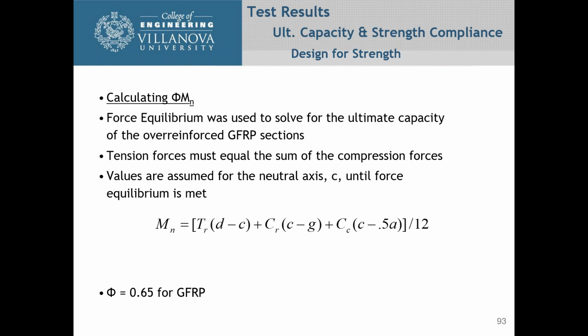You have this equation here where the moment capacity is the tensile force in the bars times the d minus c, plus the compressive force times the c minus g, which we'll show you in a second. So that is the equation from the design guides on how to calculate the capacity of a beam with GFRP reinforcement. It should be noted that the phi factor for GFRP is 0.65.